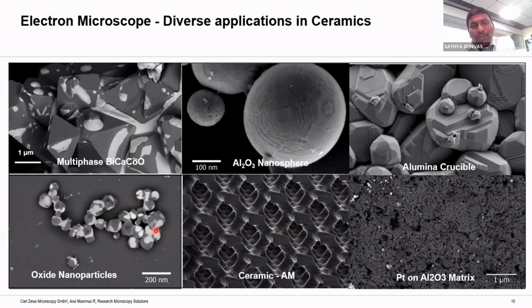So through backscattered electron imaging, you can even pick up the contrast with respect to the material. What I mean to say is, for example, with any low Z material, particularly a polymer matrix, where you introduce some conductive nanoparticles, and you want to understand the distribution of those nanoparticles in the polymer matrix, then definitely by picking up the energy selective backscattered signal through this particular detector, you can understand the distribution of those metal particles even in the polymer matrix. So with the image itself, you can clearly understand the distribution of the nanoparticles, which are higher atomic number material in a low Z matrix, which is called material contrast.